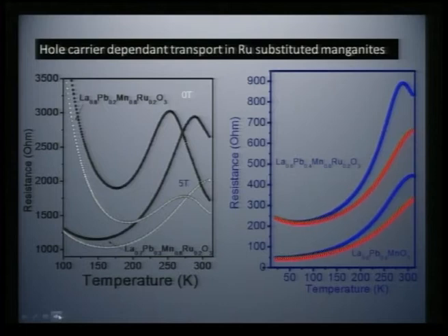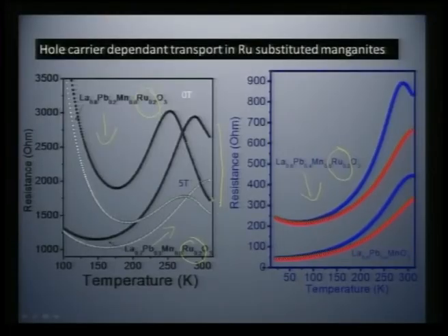We can also try to verify that by keeping ruthenium 0.2 constant in all these cases, and we can try to vary the lead concentration: 0.2 in this case, 0.3 in this case, 0.4. You can clearly see there is a change in the metal insulator transition, but nevertheless they are still ferromagnetic and they are showing a metal insulator transition. And if you also look at the fall of resistance, say for 0.2 and 0.3, there is a huge fall in the resistance for both these compositions. So, what is happening is there is an unusual correlation between manganese and ruthenium, which we should take note of, and we can try to see what exactly is responsible.